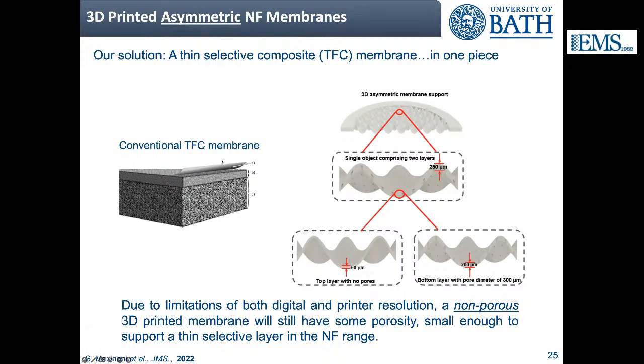And actually, we took inspiration from the way you make a thin film composite membrane. As you know, in a TFC membrane, you have the selective layer, you have the support, which has a very large porosity to limit resistance. And then you have an interlayer which bridges the gap between the very small porosity of the selective layer and the large pores of the support layer. So we did the same thing with the 3D printed support, but rather than having two separate objects, the support and interlayer, we 3D printed a single object, one where the bottom part has these very large pores of 300 microns, and the top part has no designed pores. So it's not porous in the sense that we did not design pores as we did here, but it still has some porosity, which comes from the way we designed it.